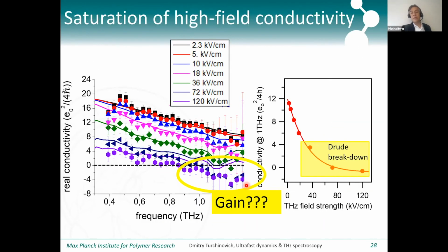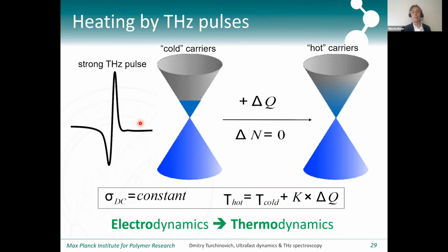So the lines that you see here are not Drude fits, but the results of a very simple calculation where we know the absorption of the graphene. The graphene absorbs a small fraction, typically a few percent, of the terahertz pulse. That is a relatively small amount of heat, and we're not injecting any carriers, so the carrier density remains constant. Although this amount of heat is very small, we're not even having microjoule terahertz pulses. These are really nanojoule terahertz pulses. But the heat capacity of the electronic heat bath is so small that we can actually get a substantial heating of the electrons in the graphene.